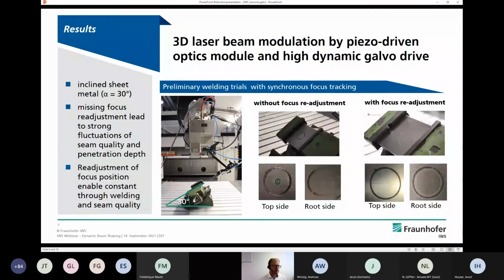We have an optical path consisting of collimation shown here, and then the 3D piezo-driven actor here for shaping the Z modulation or for moving the Z axis, and then a 2D scanner for moving the laser beam in X and Y direction. And therefore, it is already shown here, if you have no opportunity for this 3D beam shape, then you would have the issue that if you place a sheet under 30 degrees under the optics, then you would have the opportunity to weld a circle, but not with full penetration.